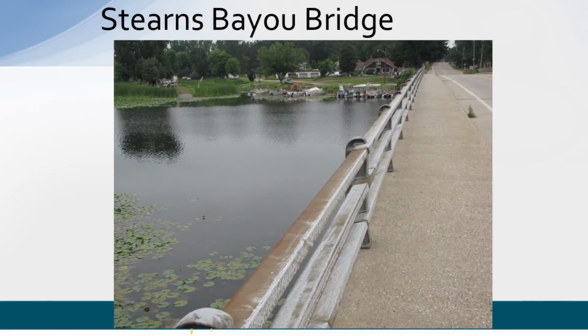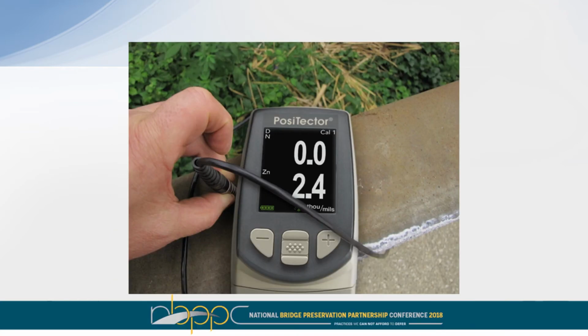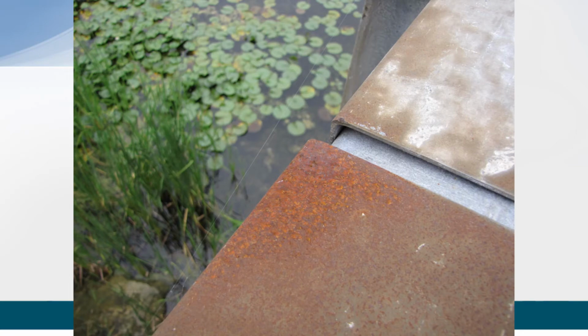But this right here is the railing that gets really hit with a lot of salt and snow from the plows. Still, even though it looks like there's no galvanizing left, there's still 2.4 mils because you're into those iron alloys that I talked about earlier in the presentation. So still 2.4 mils on this. This is a perfect system right now to go ahead and paint these railings to keep them in service. There is about 4 areas on the bridge that have these little tiny spots that are really going to have to have a little bit more attention, but it really can do it.